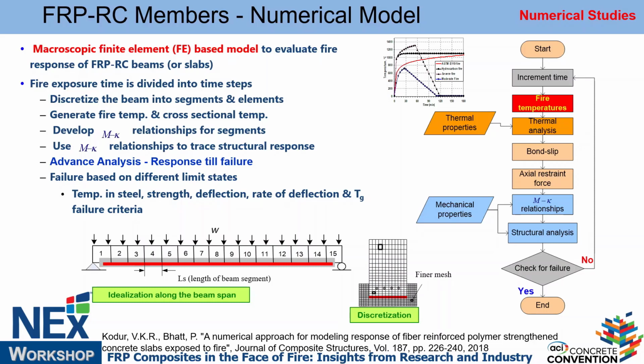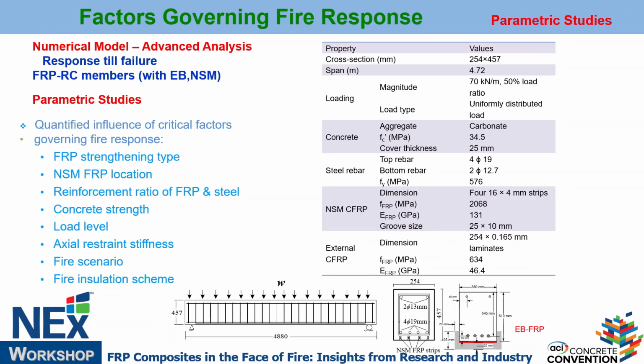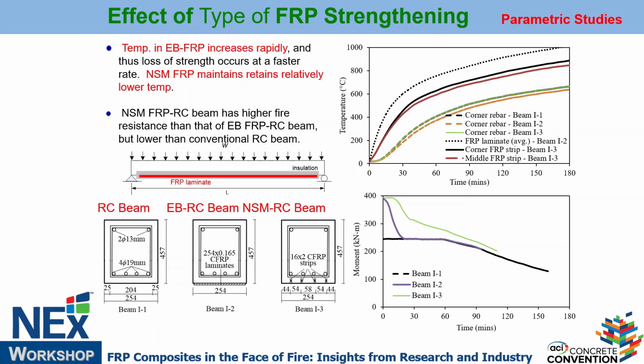But when you want to model this, concrete structure itself is hard to model, especially under fire because of spalling and other things. Additional complexities such as bond slip relations have to be incorporated. These anchorages have to be properly accounted for. It gets extremely complex, so it's hard to do in a design office. So we modeled this through finite element modeling. We developed our own models and then varied a lot of parameters to see what parameters influence so that we can engineer the system for better design, right? Rather than just using some one-point test data.